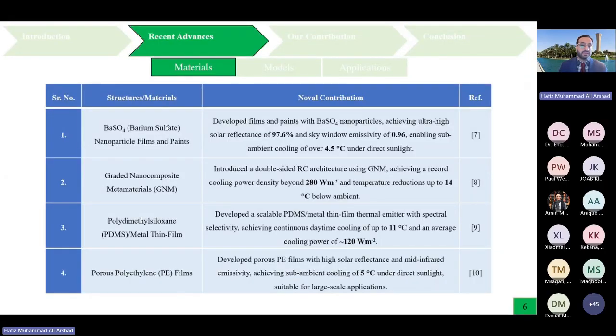Then there are some other materials like porous polyethylene films. These materials are good enough and they have a good mid-infrared emissivity for achieving some kind of subambient cooling of 5 degrees C. And most of the solar radiation that falls on these kinds of materials will mostly be reflected.